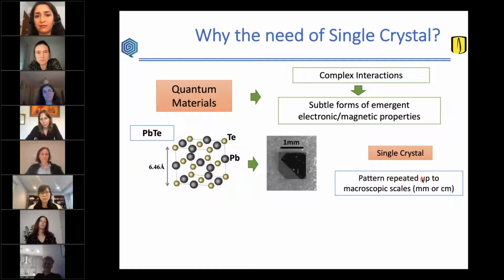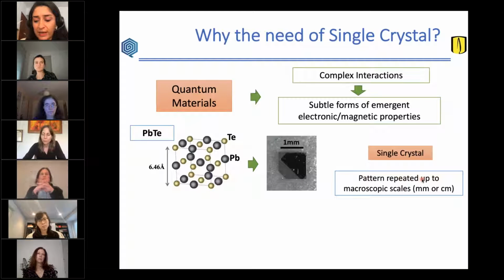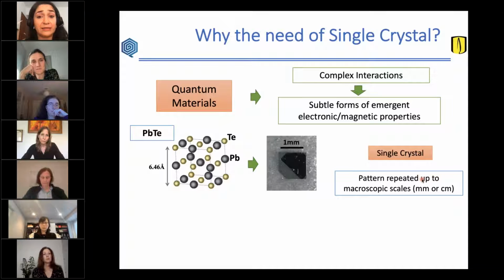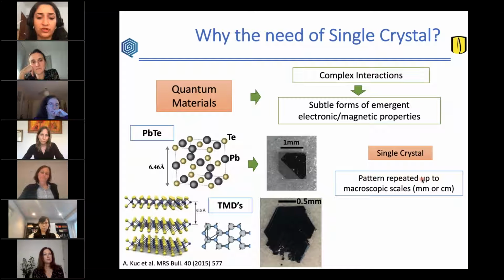So for single crystals, you probably know that we can obtain crystals in which the macroscopic shape of these crystals is a reflection of the microscopic unit cell. And in that sense, we can actually obtain very nice information, which is symmetry specific in terms of, for example, important terms in the Hamiltonians that lead to these quantum materials, which are specific to the directions or the bonds or the correlations in different directions of our material. So it is important to not lose this specificity for understanding these ground states.